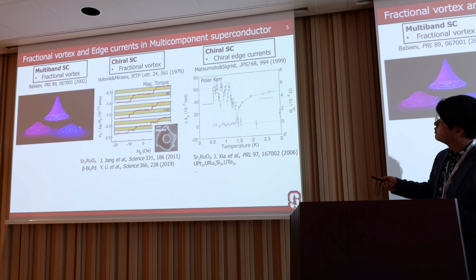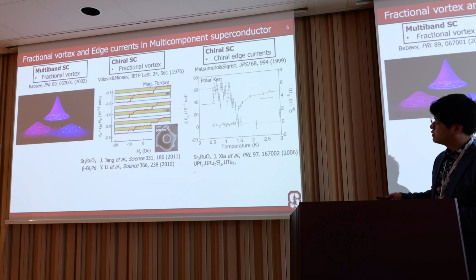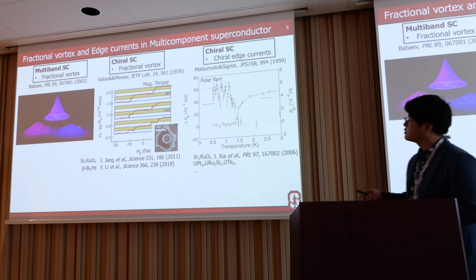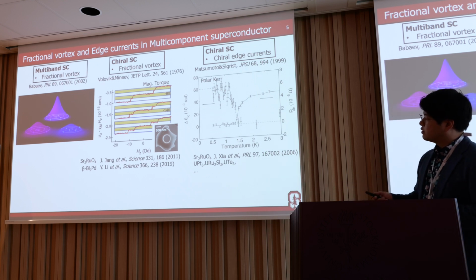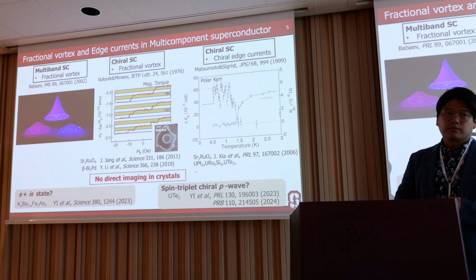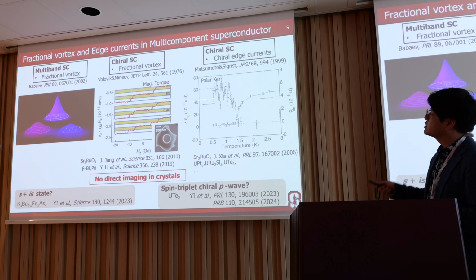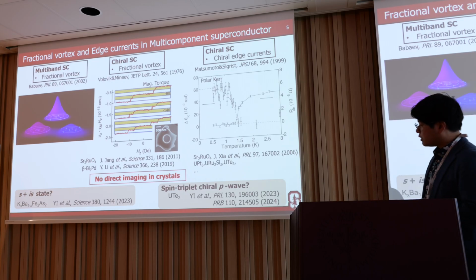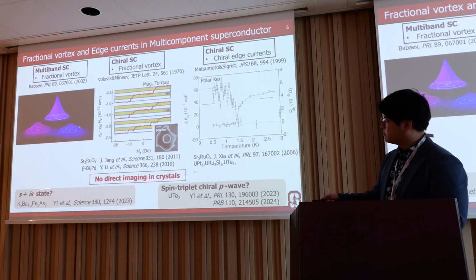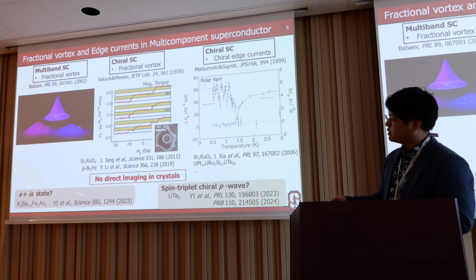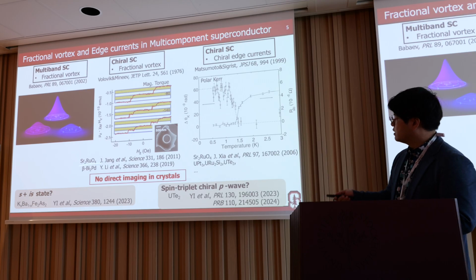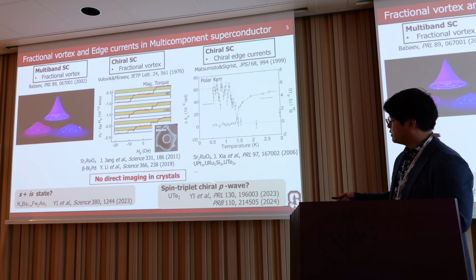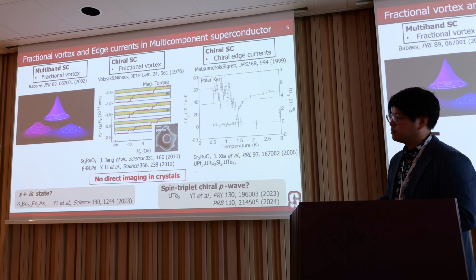But for example, the polar Kerr measurement detects a spontaneous magnetization just below Tc in strontium ruthenate or the uranium superconductor, in many samples. But also, there's no direct imaging of the fractional vortex and the chiral edge current. So today I'm talking about two samples. Potentially Ba1-xKxFe2As2 is a candidate of s plus is, and UTe2, this is a spin triplet and a candidate of the chiral p-wave superconductor.